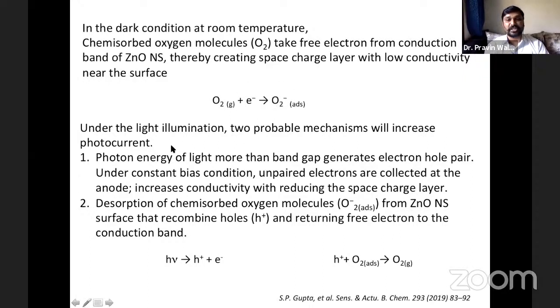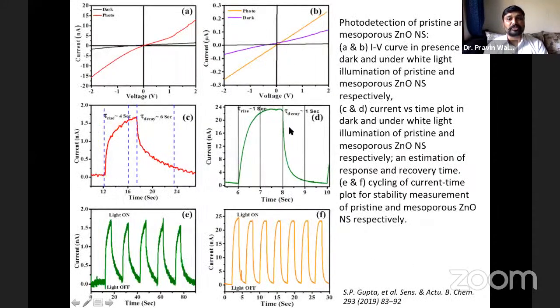And under the light illumination, there are two probable mechanisms which are happening in the photocurrent. First one is, photon energy of the light, which is more than the band gap, generates the electron-hole pairs, right? And under the constant bias voltage, unpaired electrons are collected at the anode, right? And which increases the conductivity of the cell, right? By reducing the space charge region. Another one is desorption of the chemisorbed oxygen molecules from the surface, which can recombine with the hole, right? And which returns the electron to the conduction band. So these are the two probable mechanisms which have improved the performance of mesoporous zinc oxide, which has been annealed and has oxygen deficiencies as compared to the pristine sample, right?